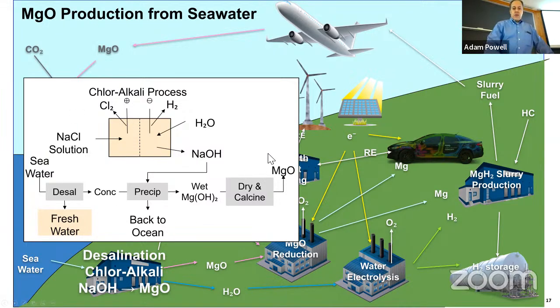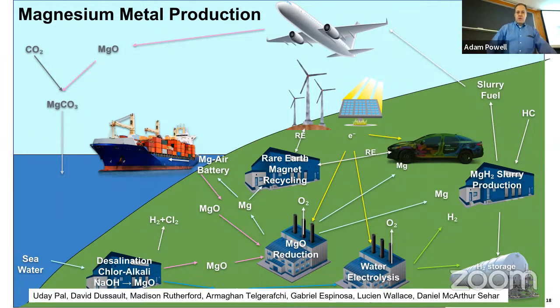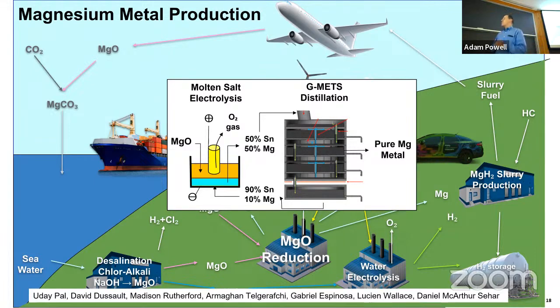magnesium oxide. You can then take that magnesium oxide and reduce it to metal through a process that's been influenced by Uday Pal, who began well before Infinium, looking at the use of this solid oxide membrane to make magnesium. The next important piece of this came from David Dussault, who was my first master's student when I was on the faculty at MIT. After leaving MIT, he developed this process for vapor compression distillation of water, and got it to very similar efficiency to membrane separation of water from, whether it's brackish water or seawater. And so that was the inspiration for this.